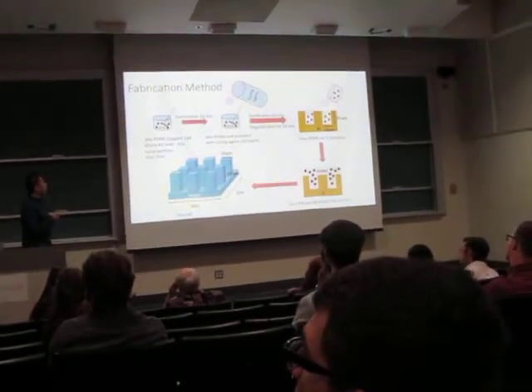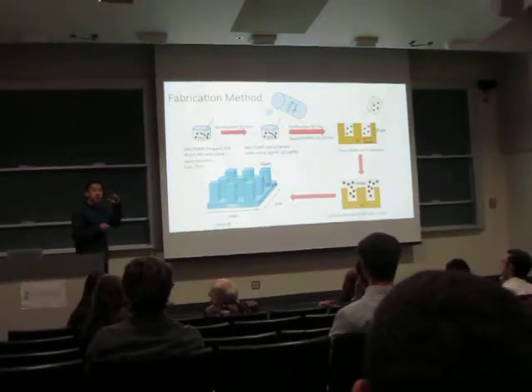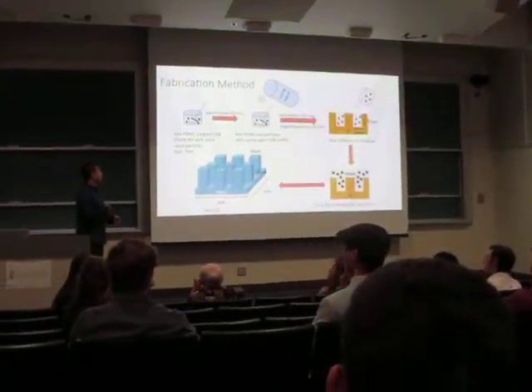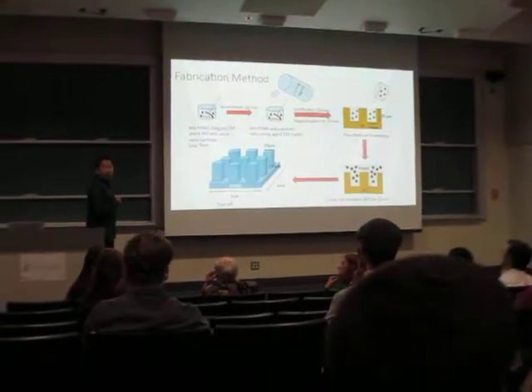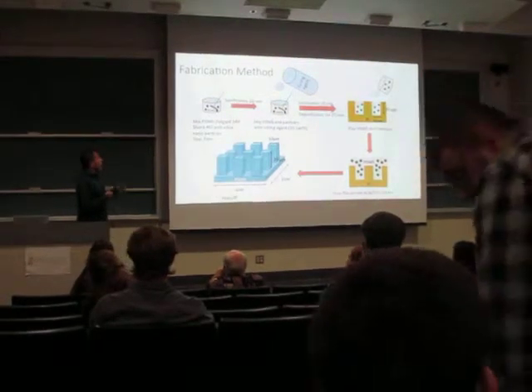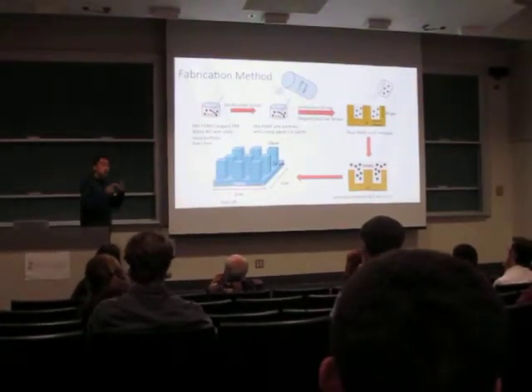We mix PDMS, which we use is Sylgard 184, Shore value 40. Shore value 40 is a measurement of the strength of the material. We mix it with silica in this case, and the size of the particle is 7 nanometers. Then we sonicate for 20 minutes to make sure those particles are evenly dispersed.